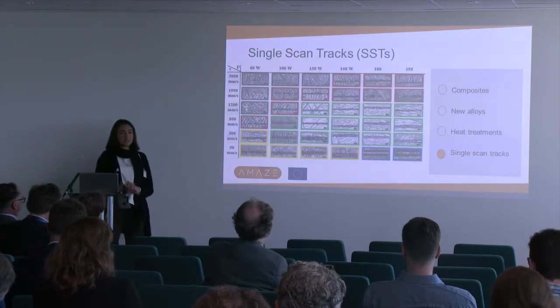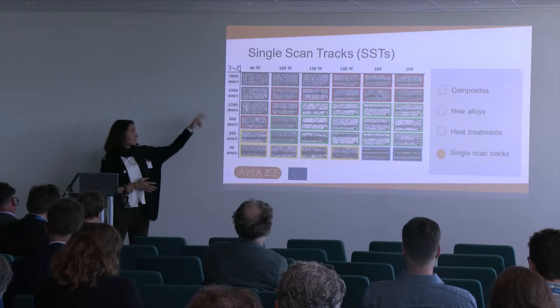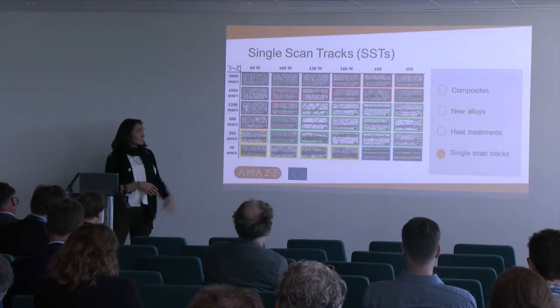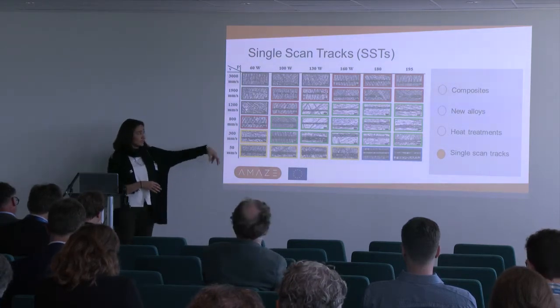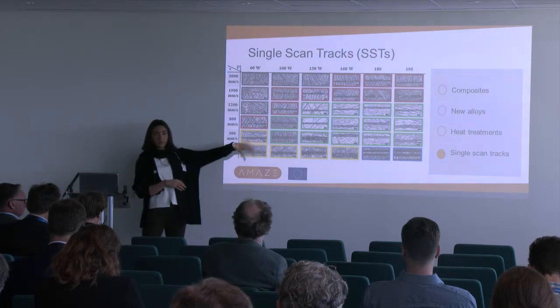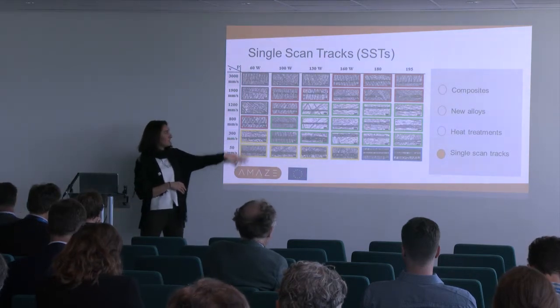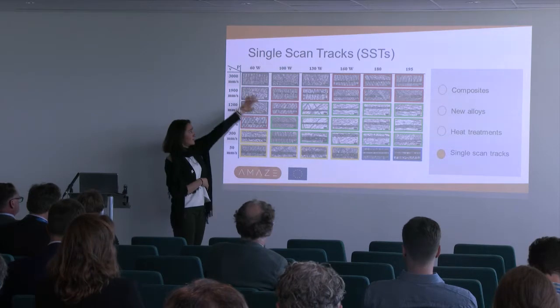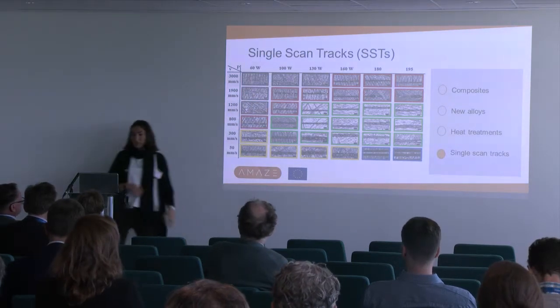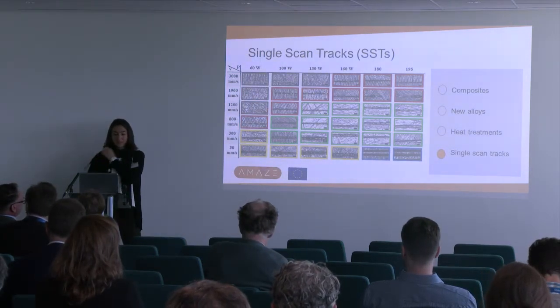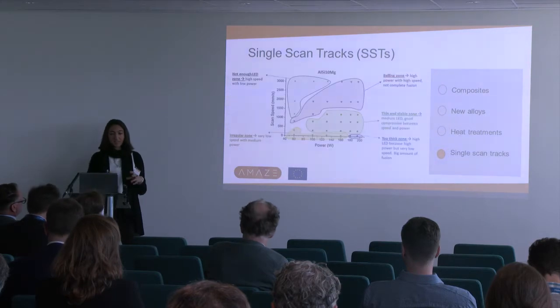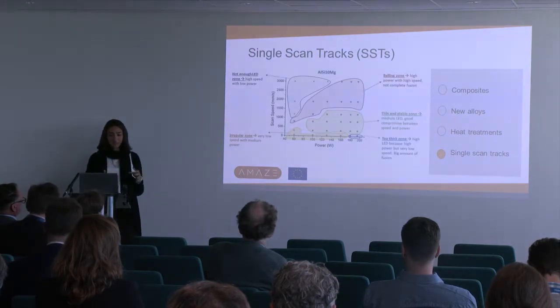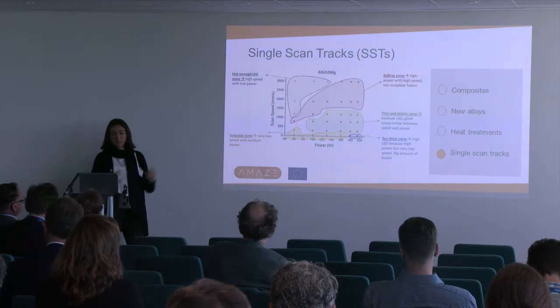If we look at the scans plotted with respect to power and scan speed, the colors are based on the stability zone. So we have here thin and stable, not enough melt, balling, and so on. We can draw these maps, which are processing maps, and we can simplify these maps with points. So we have power and scan speed and all the stability areas.